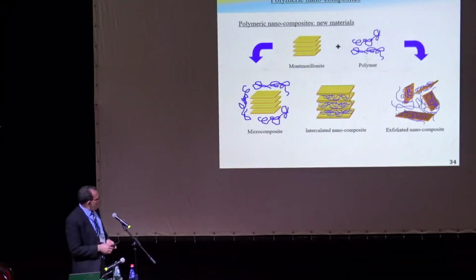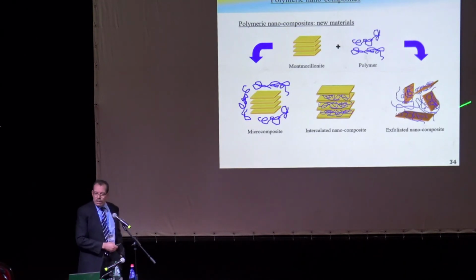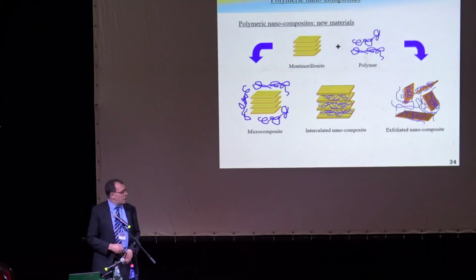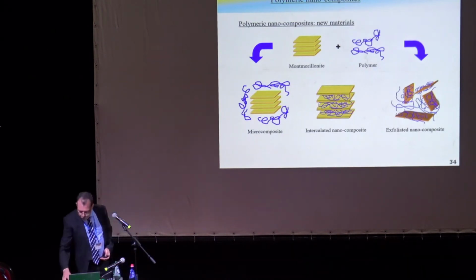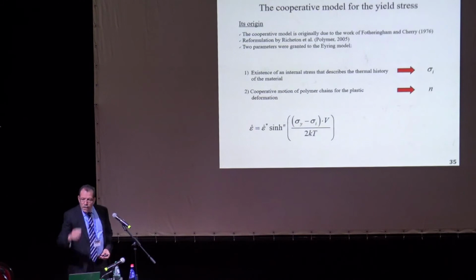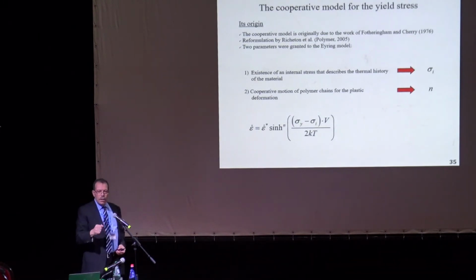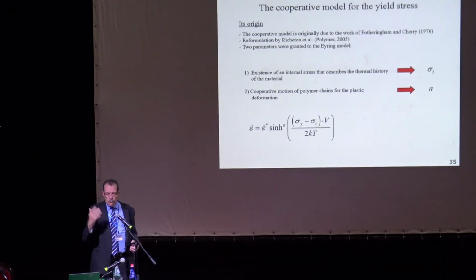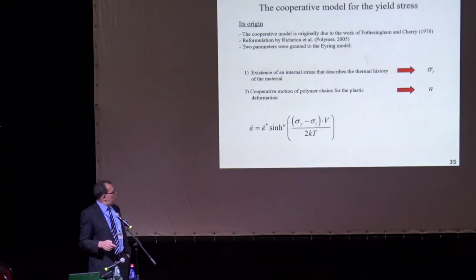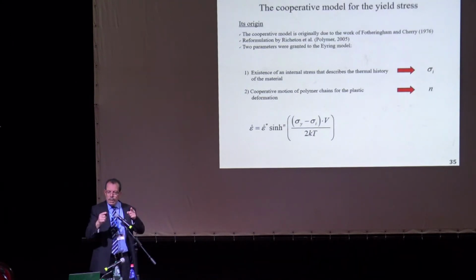And that's what you get the best out of this reinforcement in terms of mechanical properties, okay? So, in fact, when you see this microstructure, it's similar to semicrystalline polymers, okay? If you take this as a crystal. Now, for this, we are interested not in the elastic properties, but we did the elastic properties, but I will show you another model. We looked at the yield stress, the prediction of the yield stress. We were interested in a model. There are so many models that exist. One of them is called the Argon model, the Eyring model, and many others. But the problem was they were all valid within a range of strain rate and a range of temperatures, not unified. Okay? So we were looking for a unified model.